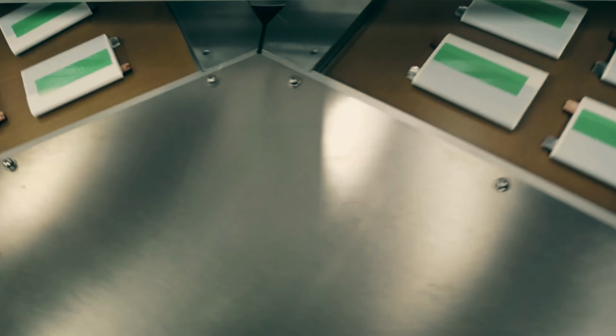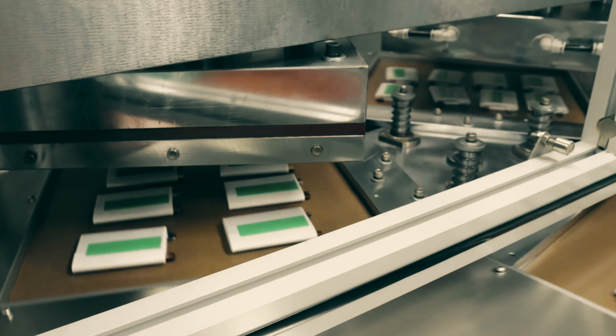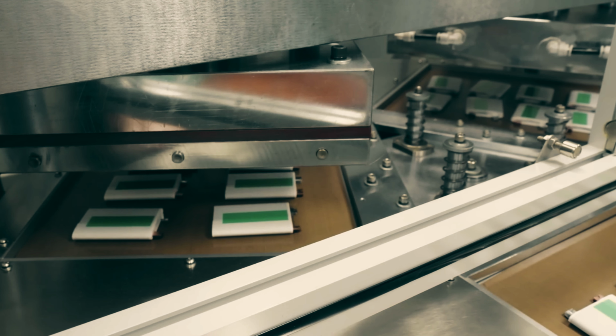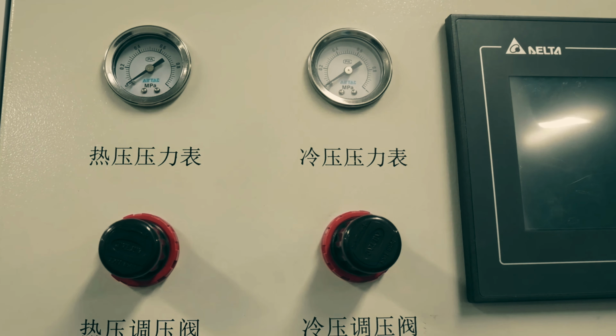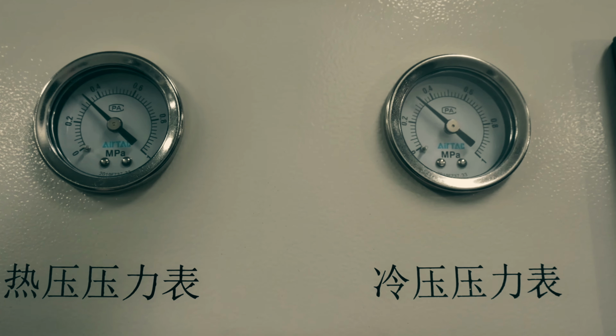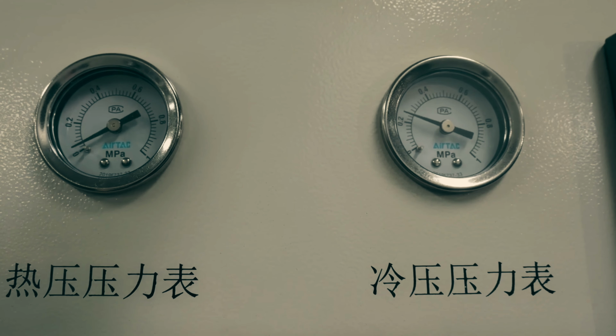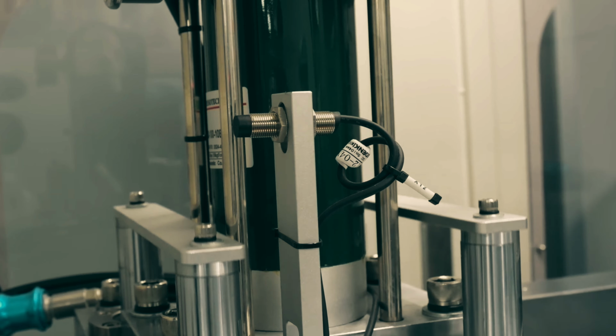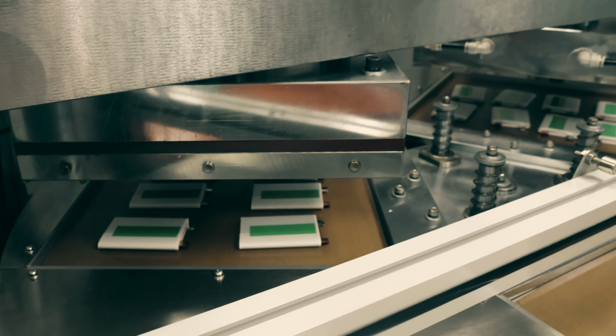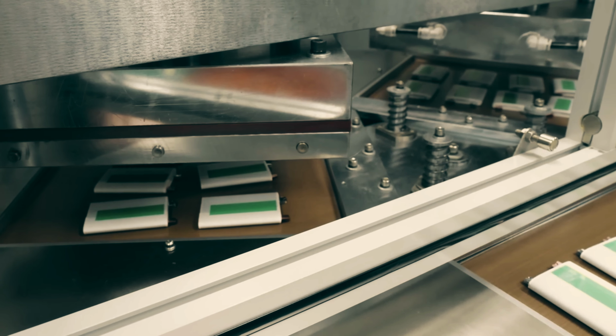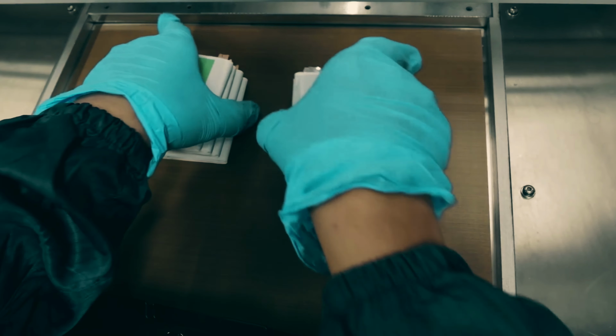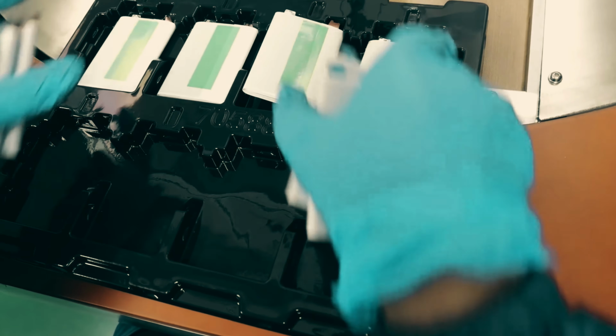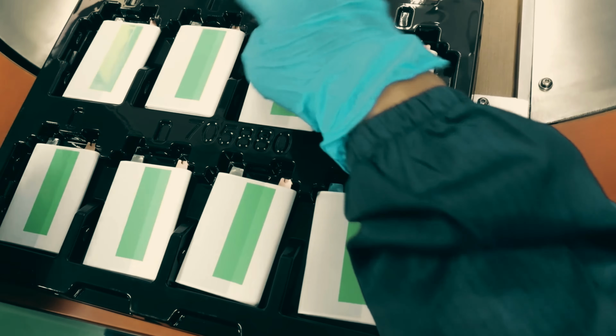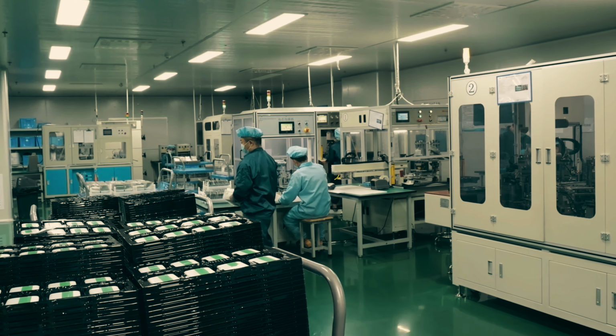Every single cell is charged and discharged multiple times during testing, checking for even the smallest voltage irregularity, capacity loss, or internal resistance spike before it's approved to ship. If even a microscopic piece of metal dust contaminates the electrolyte during this sealed process, it can create a tiny short circuit that isn't obvious right away, but can cause overheating months or years later,